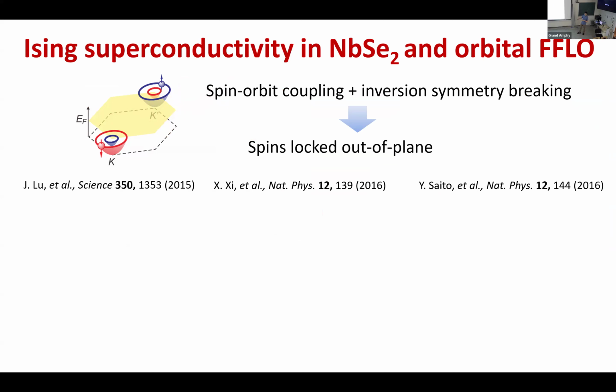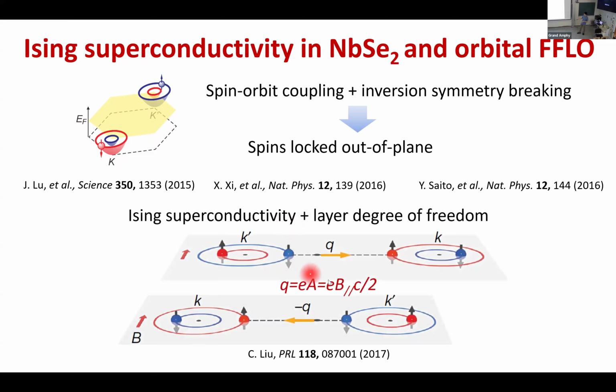When we apply the in-plane magnetic field, it cannot do anything to your Zeeman splitting, because effectively your Zeeman g is just 0. You cannot have any Zeeman splitting anymore. So what it does is that the magnetic field goes into your k, so that you have this vector potential, and that vector potential goes into your momentum. For two layers, the vector potential actually points in different, opposite directions.